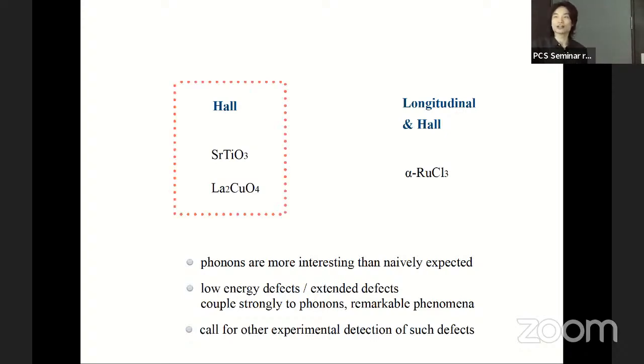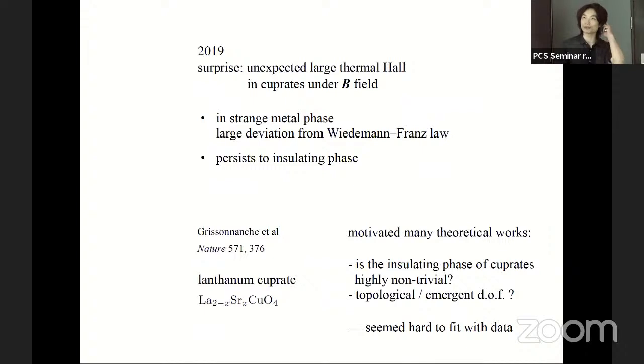So let's start with the special thermal Hall effect in these materials. Let's first review a little bit of the history of the experimental observation. There was a surprise in 2019 that an unexpectedly large thermal Hall effect was observed in the cuprates under a magnetic field. In particular, the original motivation was to look at the strange metal phase of the cuprates, which has been speculated to be related to the high Tc mechanism.